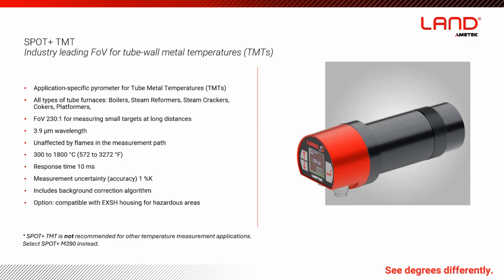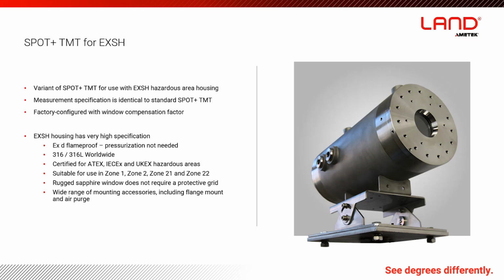And an important feature, it's compatible with our EXSH hazardous area housing, so it can be used in hazardous areas, which will typically be found in hydrocarbon applications like reformer furnaces. Just like to draw your attention to the footnote there. This is not a general purpose pyrometer. We do not recommend it for applications other than tube furnaces. That's really down to the optical characteristics to achieve the very narrow field of view we have on the TMT. We do require it to have quite a specific mounting, and that mounting is only compatible with furnace mounts.